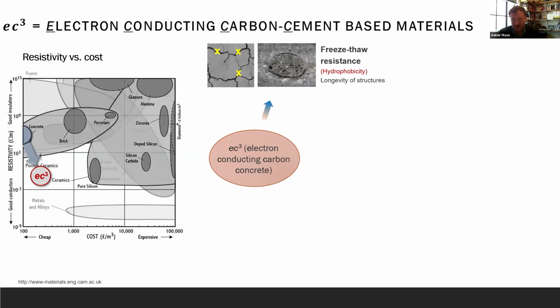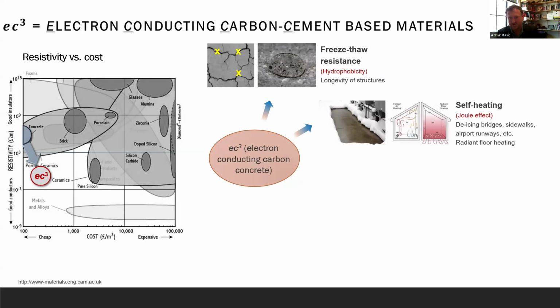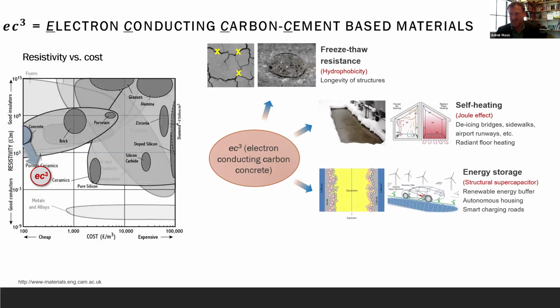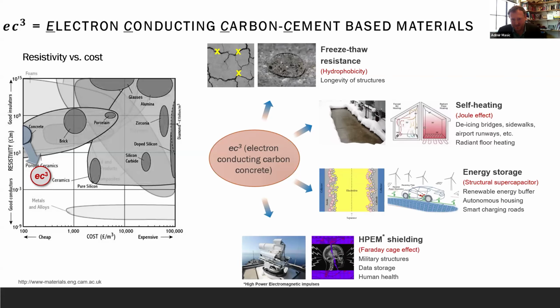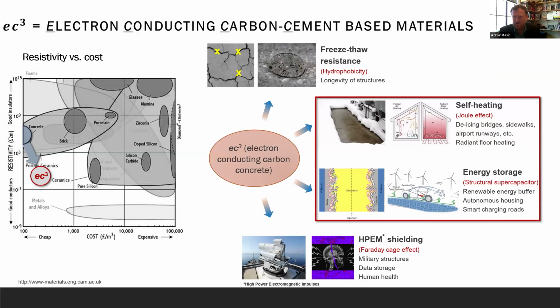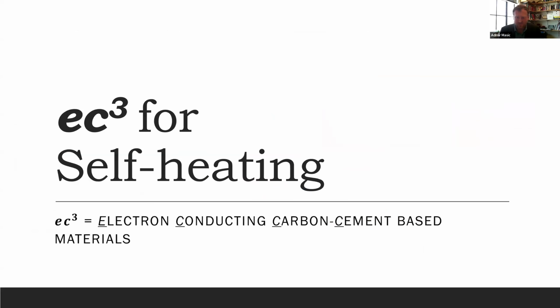Good. Applications, as I said, are multiple. You can use it for freeze-thaw resistance, and so increase the longevity. You can use the Joule effect to heat this material, which heats proportional to the voltage to the power of 2, and with a few volts, you basically get temperatures that approach 100 degrees C. Energy storage is another application, and also some high power electromagnetic shielding is possible. But let me focus on these two applications where we put significant work in.